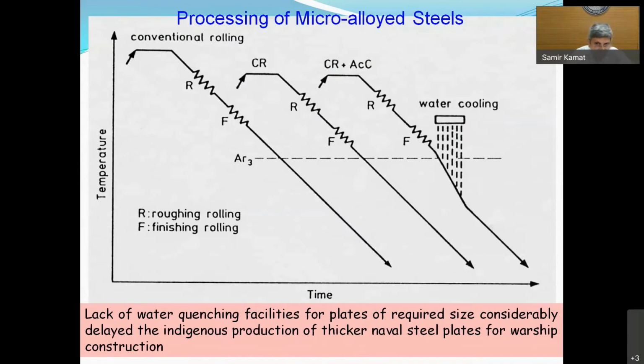And the kind of processing which is required to make plates of such steels, you need to be able to do controlled rolling plus accelerated cooling. When we started this in SAIL in early 2000s, the rolling mill at SAIL did not have the capability to do this water cooling. And hence, initially we could make only thinner sheets. But by the time I think we reached 2005 or 2006, this water cooling facility was also installed at Rourkela Steel Plant in their plate mill. And we could achieve thicknesses up to 21 or 23 mm at RSP.